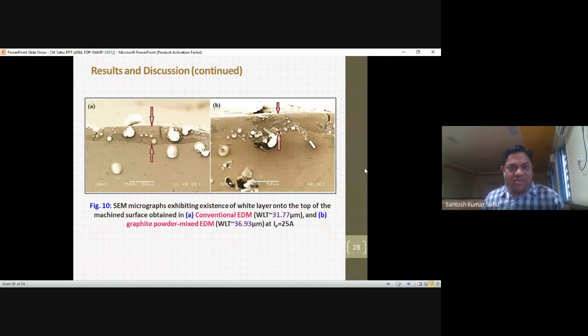Again, in this figure, we have to discuss the SEM micrograph, which exhibits the existence of the white layer thickness on the top of the machined surface. In figure A, the left side is conventional EDM. You measure the white layer thickness as about 31, and by adding the graphite powder, we see that the white layer thickness increases. But again, the white layer thickness increases, and that is one type of limitation. But due to the addition of the graphite, it increases here.